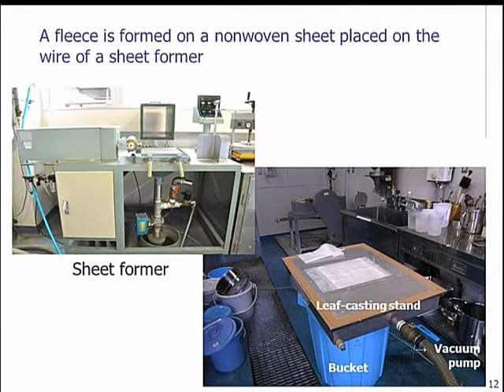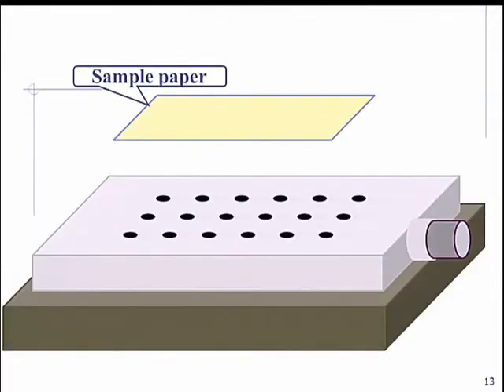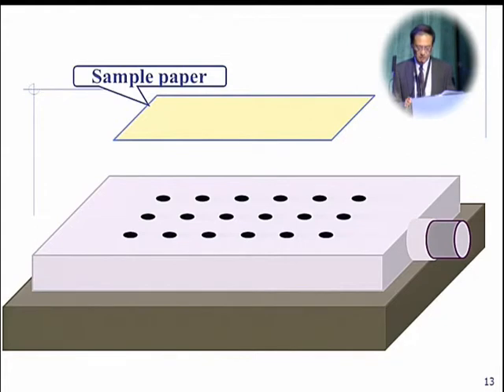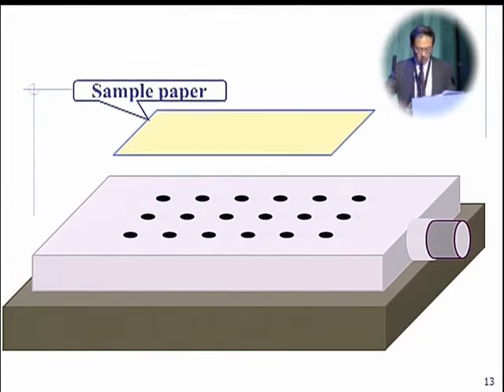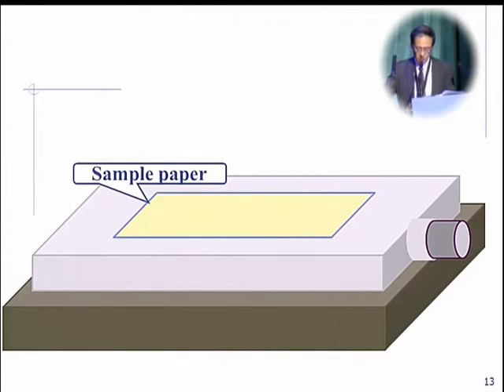The fleece method used at the Kochi Prefecture Paper Technology Center is very simple. We used a sheet former, a leaf casting stand, a vacuum pump, and some buckets. A fleece layer is formed on a non-woven sheet placed on the wire of a sheet former. The paper to be treated is placed on a leaf casting stand, and a small amount of water is poured onto it. After the application of gentle suction, the fleece layer on the non-woven sheet is placed on the sample paper, fleece side on paper side.